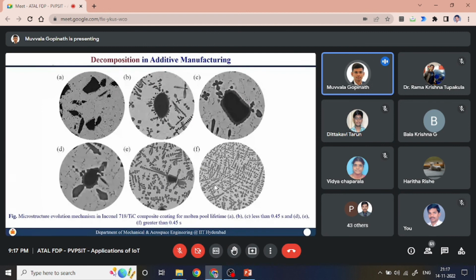So if you see whatever I have represented in the pictorial way, you can see over here, the wetting has started, and as the molten pool lifetime increases, a proper shell core structure has formed in these two. But beyond this particular molten pool lifetime, if you extend it further, you can see the decomposition of the ceramic particle is happening and the dendritic structure is forming. And if you continue further, the whole ceramic particles will decompose and then you will have a ceramic dendritic structure like this. So all these dendrite structures are ceramic in nature, making the material brittle and changing the chemical composition of the material.